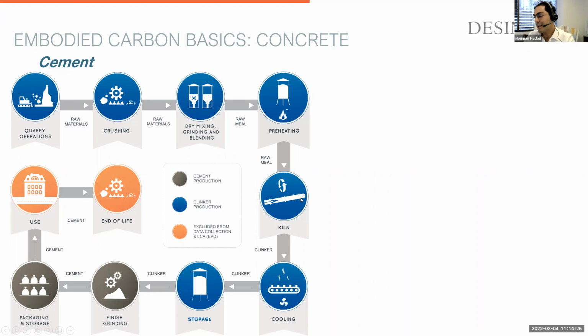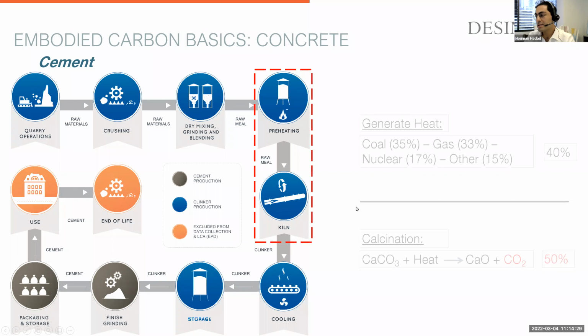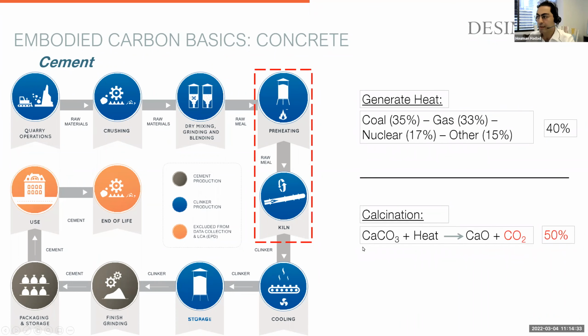For the two processes of preheating and cooking the cement, you have to generate heat for preheating and for cooking, right? It's mostly either fossil fuels, or recently it's becoming more and more common to use gas, nuclear energy, and other sources like wind energy and whatnot. So that's one way that you're releasing CO2 in the process. The other way is a chemical reaction, calcination in the kiln, when you are cooking the limestone. Essentially you are releasing CO2, which is an unwanted byproduct, and you end up with the lime. That also releases CO2 into the atmosphere naturally, and that's sometimes more than the CO2 that you consume just to burn or heat up the kiln and preheating process.